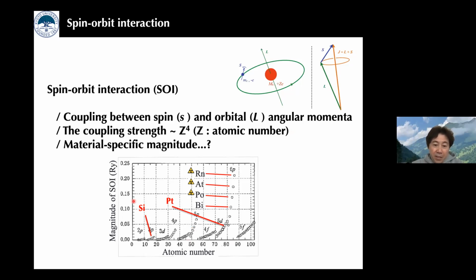In fact, theoreticians carried out calculations of the magnitude of the SOI as a function of the atomic number. As you can see, in principle the magnitude becomes larger when the atomic number increases, but it depends on the outer shell electrons. But anyway, we can roughly say the heavier element induces larger spin orbital interaction, namely efficient spin conversion. The third important thing is that until recently, people believed that the magnitude of SOI is material specific, and we cannot control it. But our achievements overturn the conventional understanding of these things.